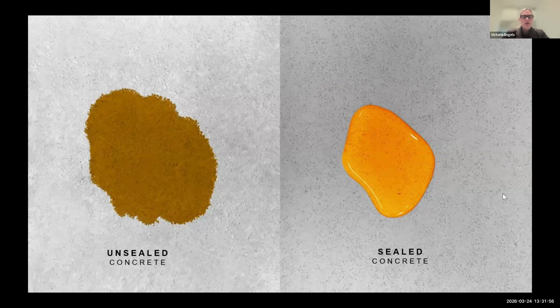This image depicts the same concrete panel, except the right side has been sealed. You're going to notice on the left-hand side that the color seeps into the raw concrete, while on the right side it beads off the surface, and that's because the surface is treated. You're going to notice also that the addition of the sealer enhances the color of the material. A good sealer is going to compensate for concrete's porosity, and for wet applications such as countertops and sinks, a proper seal is critical. It's like the top layer of a clear coat on a freshly painted car. With proper care and maintenance, it's going to last for years.